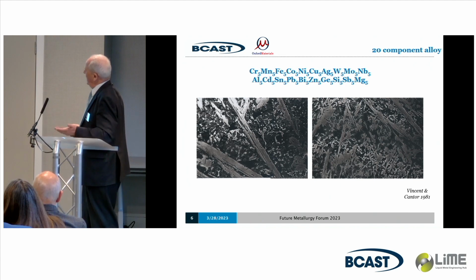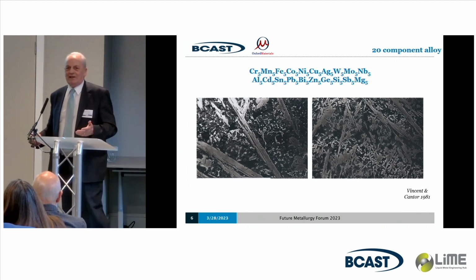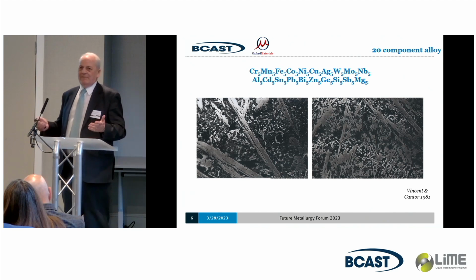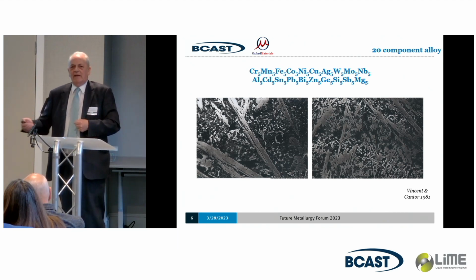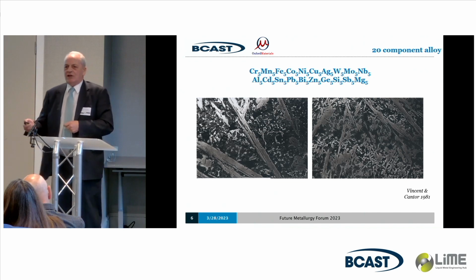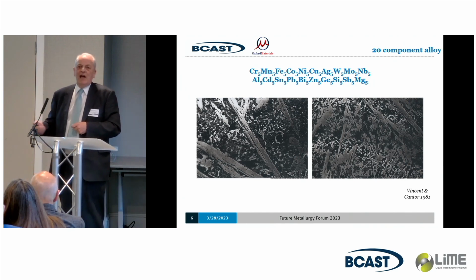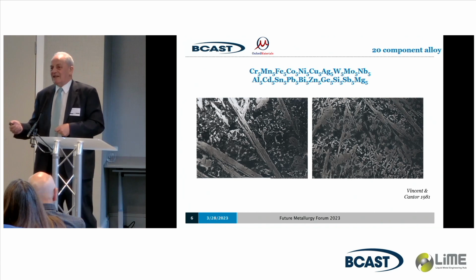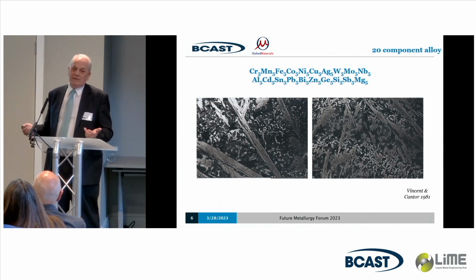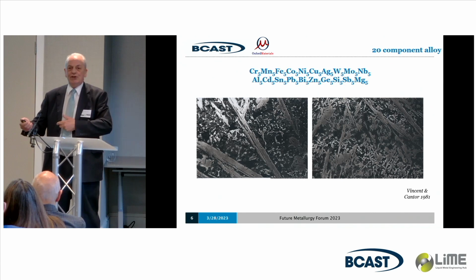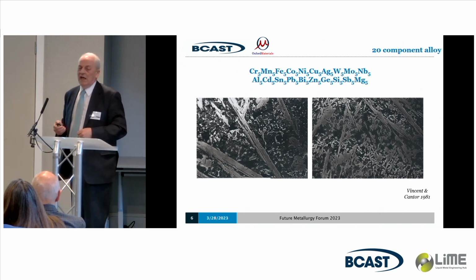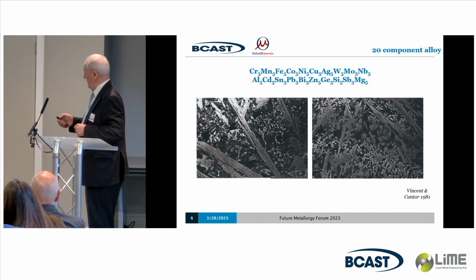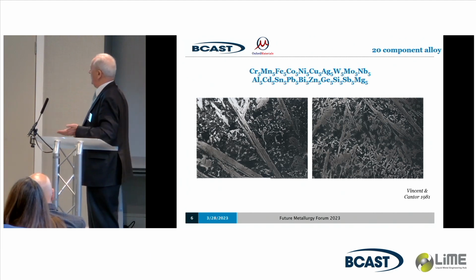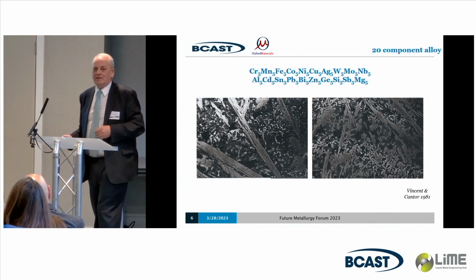It's rubbish, right? It's loads of complicated components, loads of compounds. Because the reason people didn't: if you add tin to copper, you start to form a compound which hardens the material. If you add carbon to iron, steel, you start to form a compound cementite or maybe graphite which hardens the material. If you add too much, it hardens it so much it becomes totally brittle. It breaks apart when you make it. And that's what happens if you add too much or you have too many components. But people didn't go far enough, as you shall see in a minute. But the first thing we seemed to discover was everyone was dead right. This is rubbish. It broke up, it cracked up, it was not a good material.